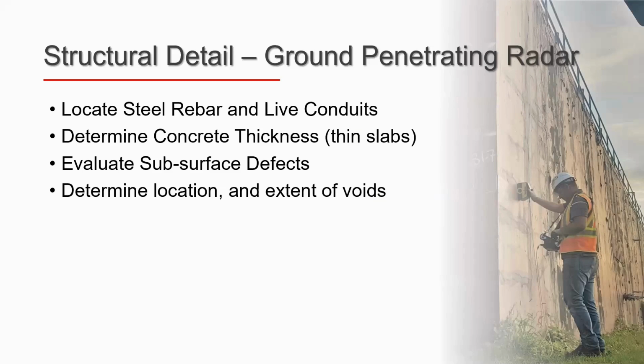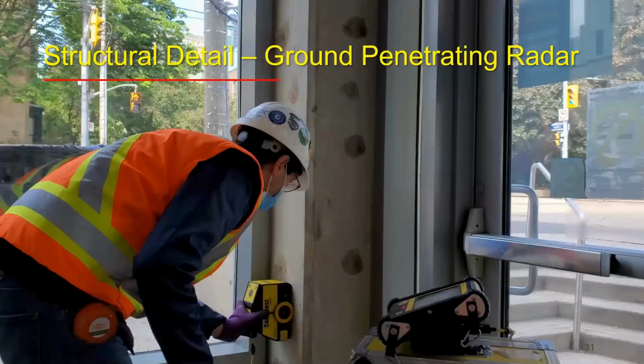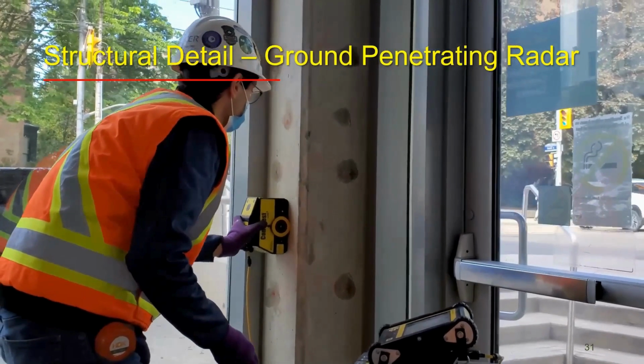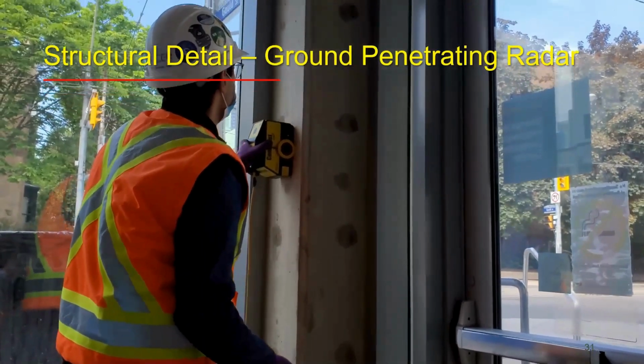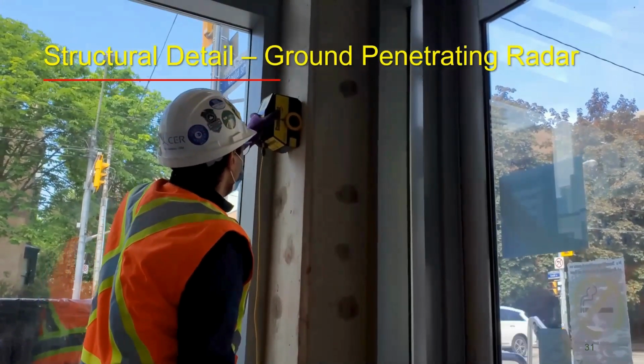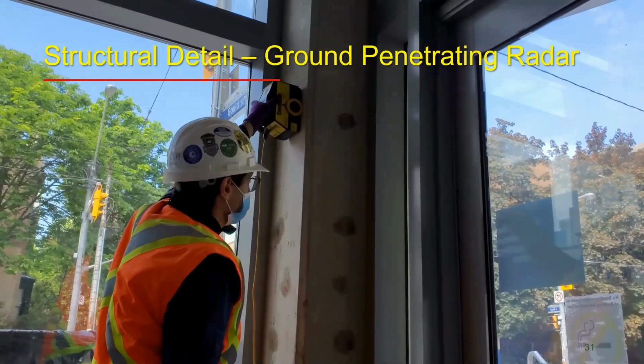Nowadays, most cutting and coring companies are equipped with different sorts of GPR units, and it will help them verify the location of steel reinforcement ahead of drilling, so they avoid cutting steel reinforcement, or they avoid cutting the live conduits in the concrete slabs. So in this most basic application, the GPR can be used to identify the location of the steel reinforcement. If you have the capability to calibrate the test results, then the test results can be used to get an estimate of the depth of steel reinforcement.